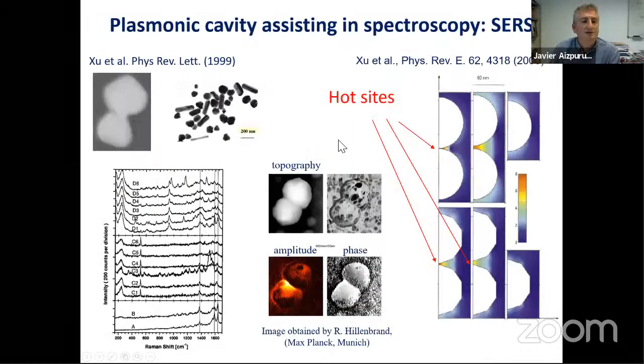People have seen this, as I tell you, almost with surfaces in the 70s and 80s, but with nanoparticles and nano antennas 20 years ago, the group of Mikael Käll in Sweden, for example, was using this type of junctions. Here on the top left, you see two metallic nanoparticles. They act as a nano antenna. Light comes in, it's getting trapped here in the middle. You can see actually a near field optical microscopy image of this trapped light in the junction. Now, if you put here hemoglobin like they did, you see that the signal, the vibrational fingerprints, the vibrational modes of this hemoglobin are boosted just thanks to the action of this trapped light, which is probing more effectively the hemoglobin that is particularly located in the middle of the gap, okay?